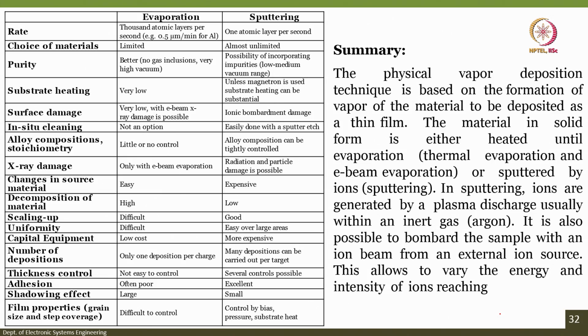So when we talk about scaling up, it means to have bigger substrate and other things, right, for sputtering it is really good, but in case of the evaporation it is very difficult to scale up the system. When it comes to uniformity, again the evaporation system is difficult, while the uniformity of the film in case of sputtering will be better because the sputtering is a mechanical way of depositing the atoms onto the substrate by dislodging the atoms using the ions, and these ions are from the argon.